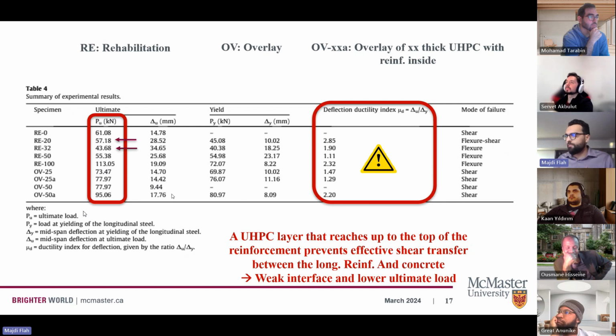So the authors investigated that the UHPC layer that reaches exactly up to the top of the reinforcement is going to prevent the shear transfer between the longitudinal reinforcement and the concrete, which will lead to a weak interface and lower the ultimate load. So the idea behind this study is we can provide reinforcement as long as we respect the minimum cover between the edge of the rebar and the interfacial transition zone.